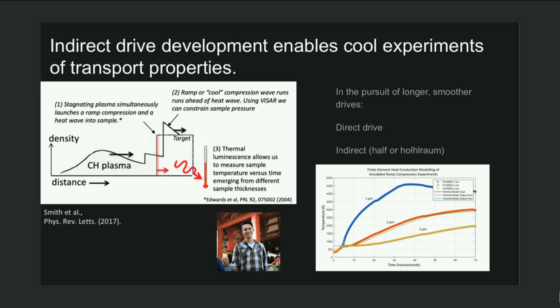So it turns out this was a technique people tried to develop to create longer and more stable drives, but they realized that the heat wave, because this hot plasma was touching, also catches up through the sample. And so one experiment's loss is another's gain, and now we have a way to get at thermal conductivity if we do our experiment right. And so a project that one of my graduate students is attempting is to use these types of experiments to try to constrain the thermal conductivity of iron at planetary interior conditions. But we don't know if it's going to work or not, so stay tuned for that.